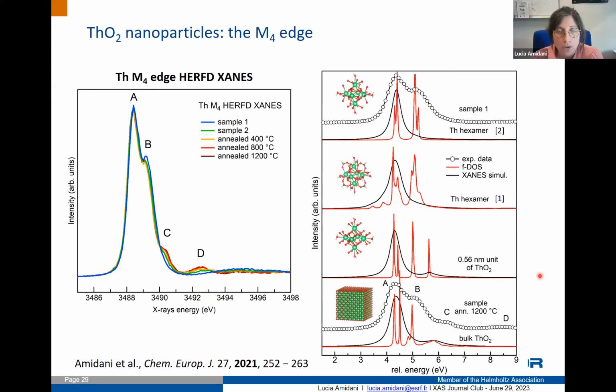And what if I go for the real clusters? Because those clusters have structures that have been published. And here, if I take the clusters that have been measured, I indeed miss the 3rd peak. That is what I see. This 3rd peak is peak C in my experimental data.